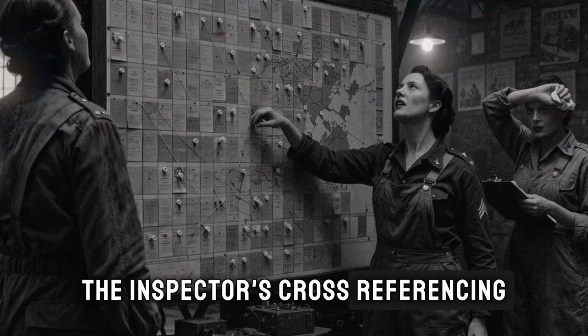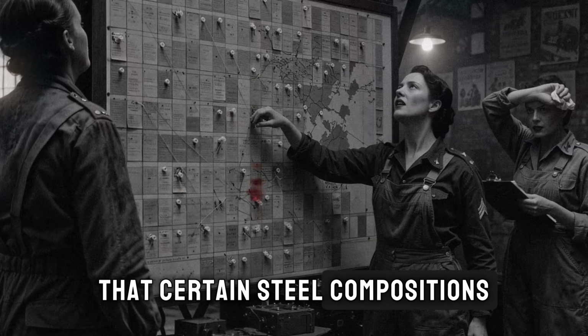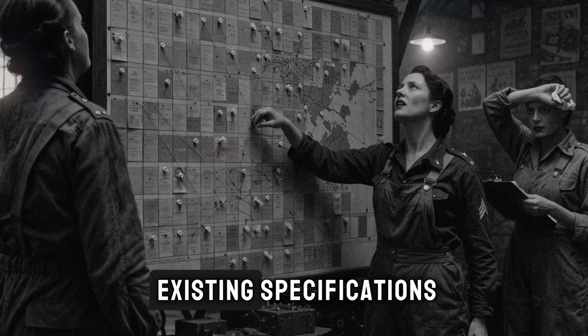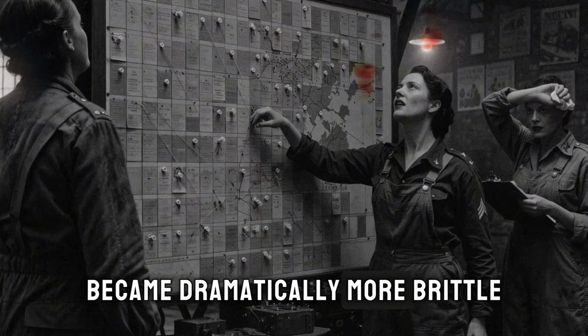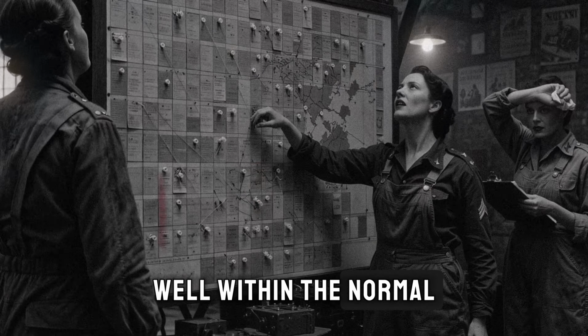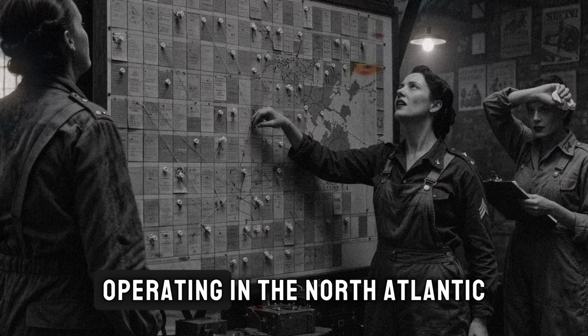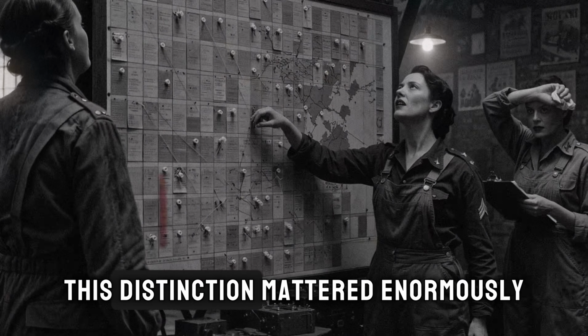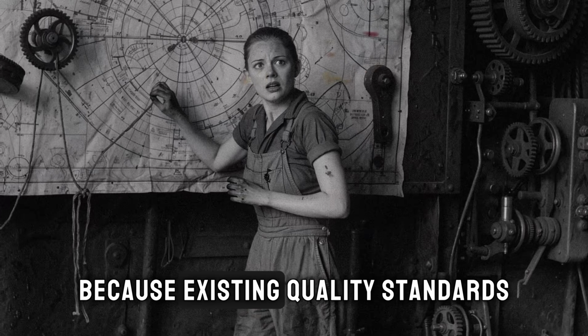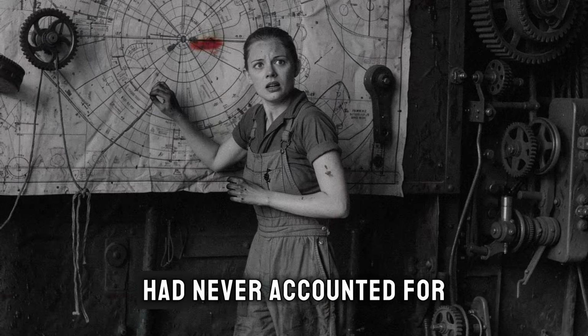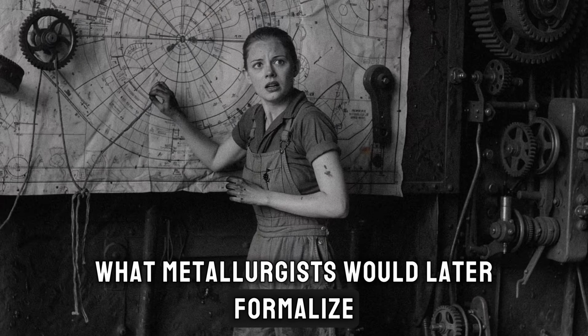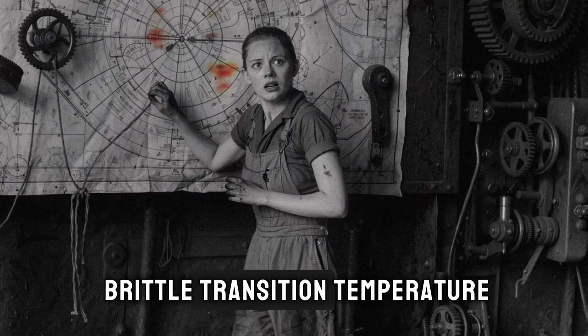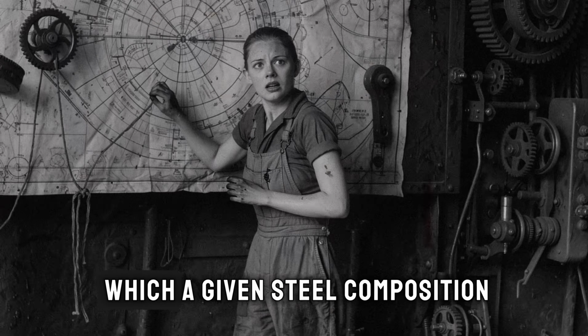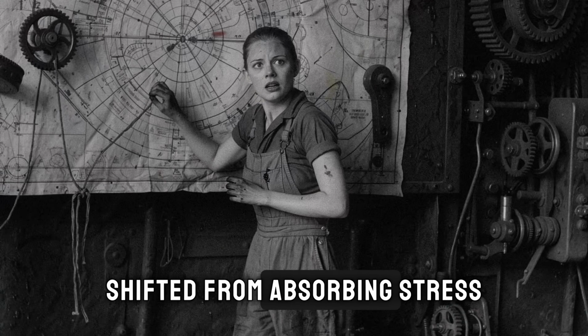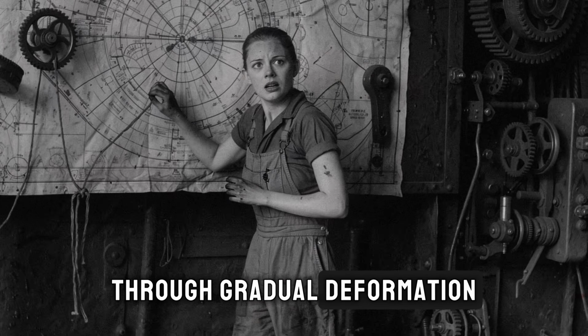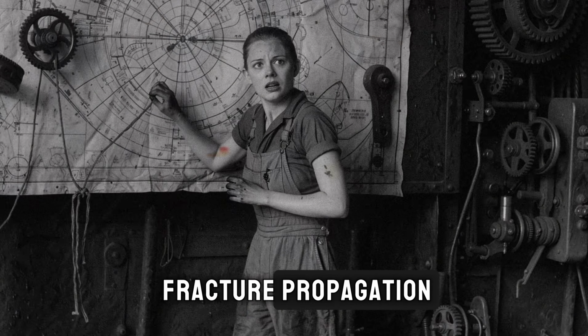The inspectors' cross-referencing suggested instead that certain steel compositions, all technically compliant with existing specifications, became dramatically more brittle at temperatures well within the normal range Liberty ships would encounter operating in the North Atlantic. This distinction mattered enormously because existing quality standards for shipbuilding steel had never accounted for what metallurgists would later formalize as the ductile to brittle transition temperature, the specific point at which a given steel composition shifted from absorbing stress through gradual deformation to failing suddenly through fracture propagation.